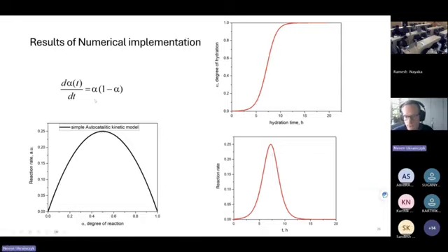So you can go from the model to, for example, the calorimetry results. And also what I showed you, you can go back from the calorimetry results. If you divide by the total heat, you can go to this kind of representation where you have the rate as a function of degree of reaction, because this is what you need for the models. If you want a fundamental model, you should have degree of reaction. You should not have time in the model.